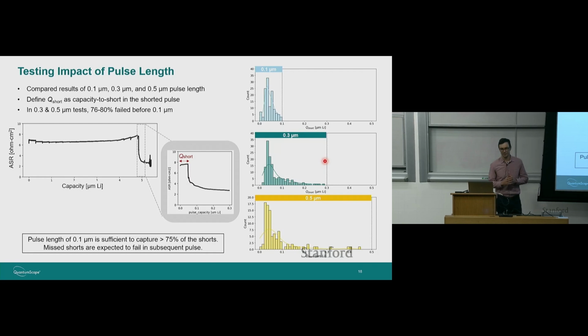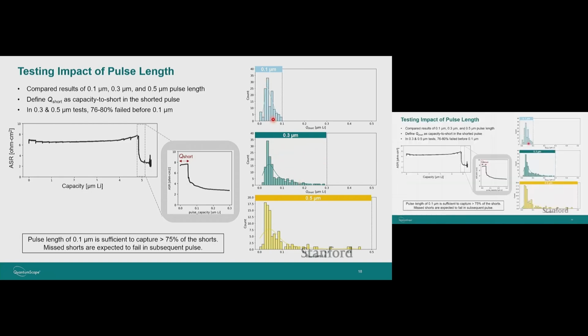Short answer is we picked a value that we're confident is valid. And the way that we assure ourselves that it is valid is we look at this failure fraction over time as we're applying current density. And we pick a time in which most of the failures occur, if they're going to occur at that current density. So we're showing 3 different durations of the test, and showing that even in a long test, almost all of the failures happen early. So we can be confident that we are recording a failure if the device is going to fail at that given value of stress.